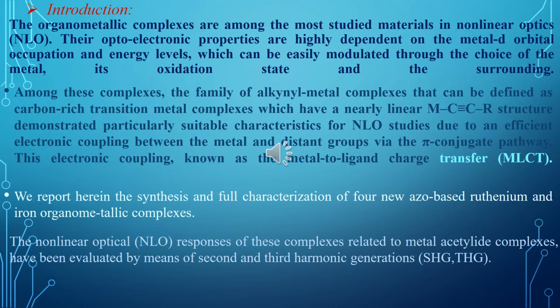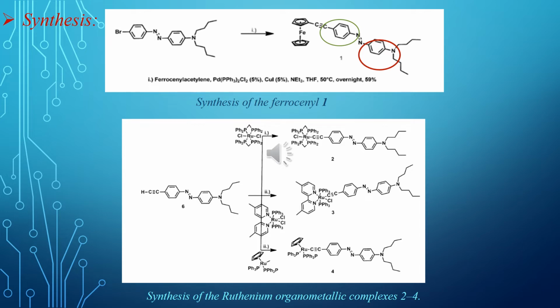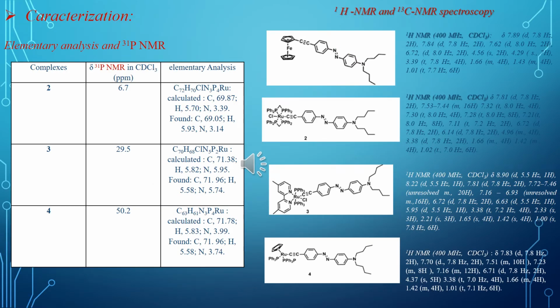We report herein the synthesis and full characterization of 4 new azo-based ruthenium and iron organometallic complexes. The nonlinear optical response of these complexes relative to metal acetylide complexes has been evaluated by means of second and third harmonic generation. The compound 1, a ferrocenyl derivative, was synthesized via the Sonogashira reaction. 3 ruthenium complexes, 2, 3, 4, have been prepared by a 2 step procedure reported in the literature. These new complexes were characterized by microanalysis and NMR spectroscopy of hydrogen, phosphorus, and carbon.